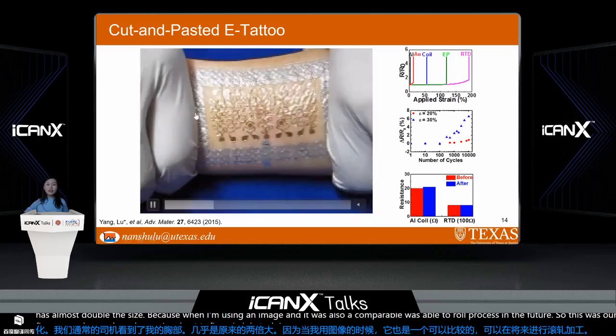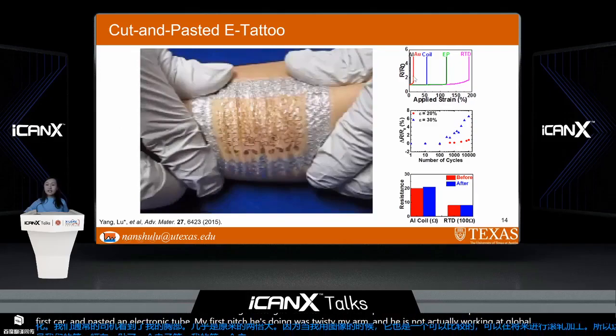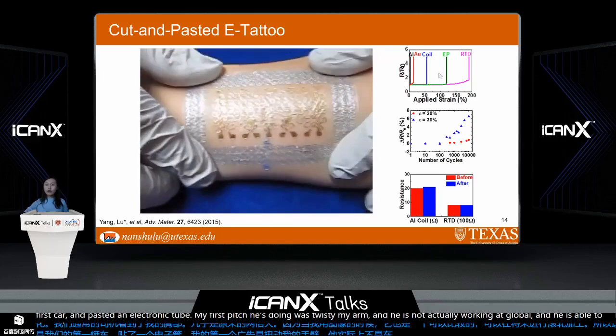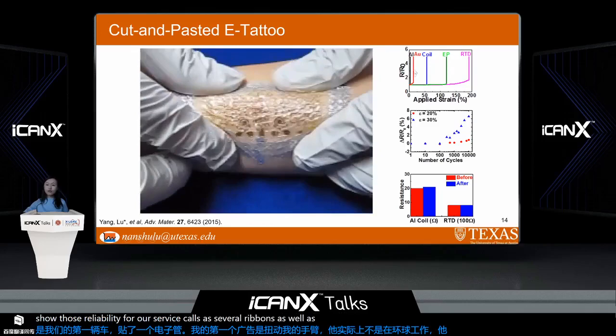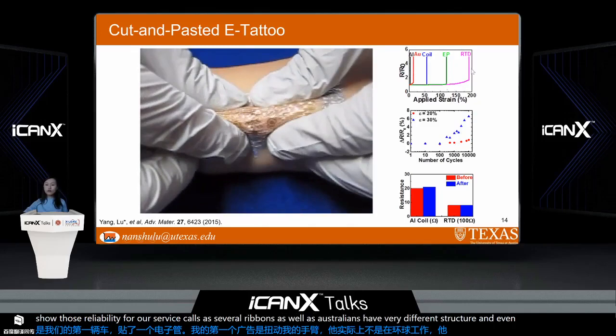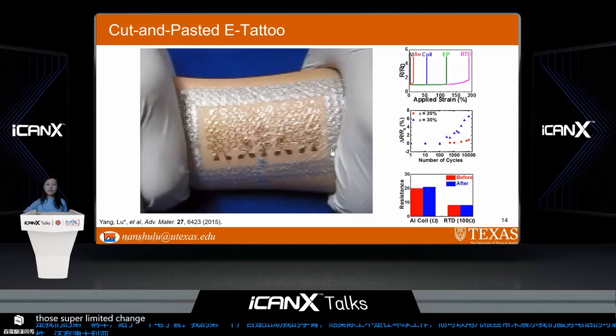And he is able to show the mechanical reliability: serpentine ribbons as well as straight ribbons have very different stretchability. And even after 10,000 cycles for those serpentine ribbons, there is limited change in resistance. Before and after skin deformation, there is also almost no change in resistance.